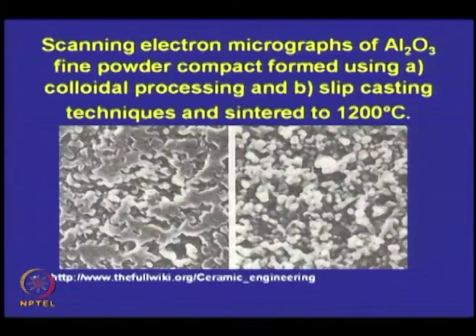Look at the difference in microstructure. The one on your right, which was slip cast, shows that sintering has not even started. Whereas the one on your left, which started off with identical powder sizes, we see a large number of grains growing.